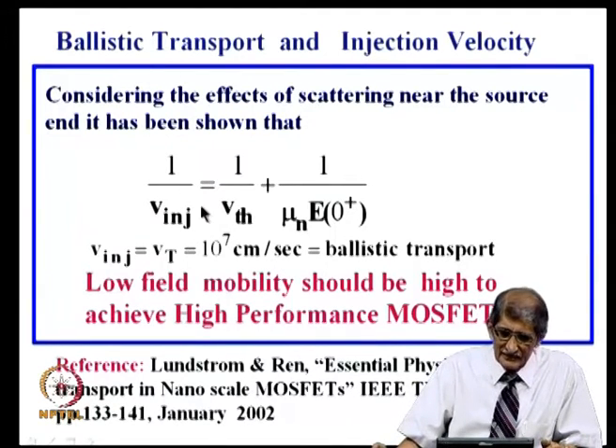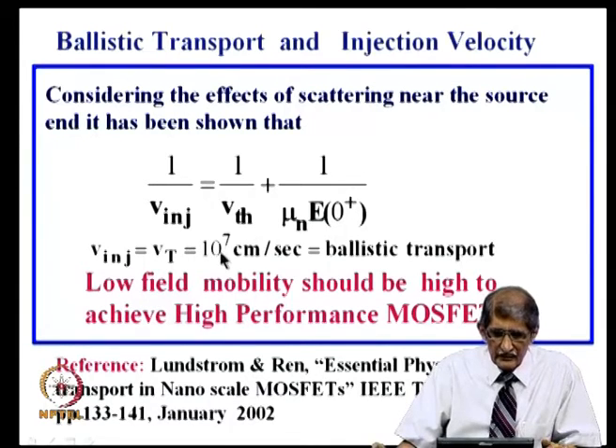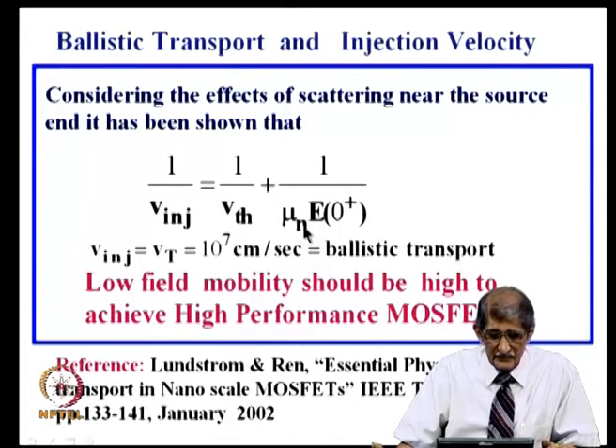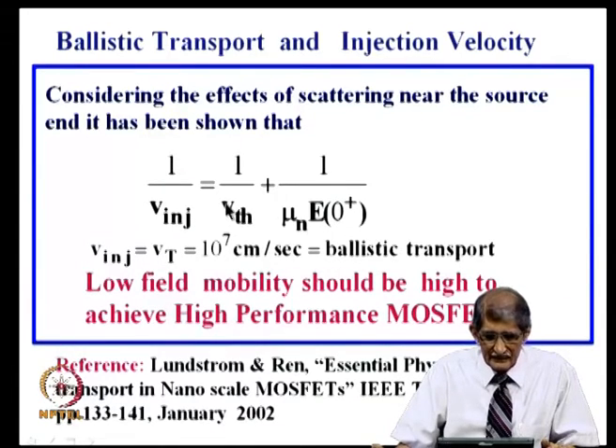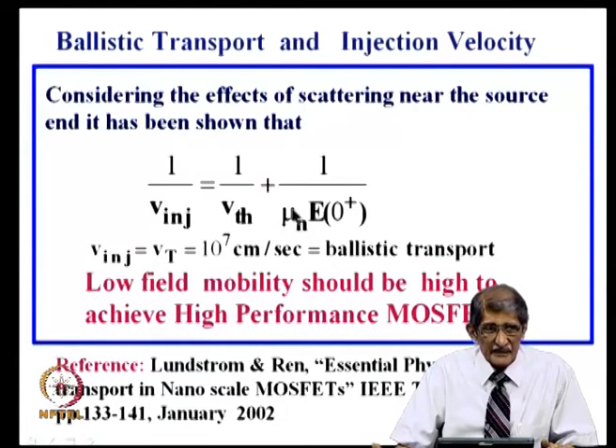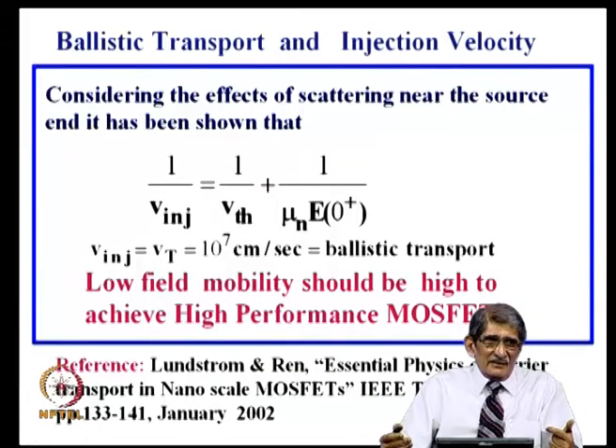So, injection velocity is controlled by these equations. That is thermal velocity, which is 10 to the power of 7 centimeter per second. If there is no collision at all after injection, that would have been 10 to the power of 7 centimeter per second. But because of the combined effect of the scattering, you get injection velocity less than the thermal velocity. You can see that if the mobility is very, very large, if the mobility is very, very large, it could be that in that electric field, okay, you will have, it is like putting two resistors in parallel. The resistance is governed by the resistance which is lower.